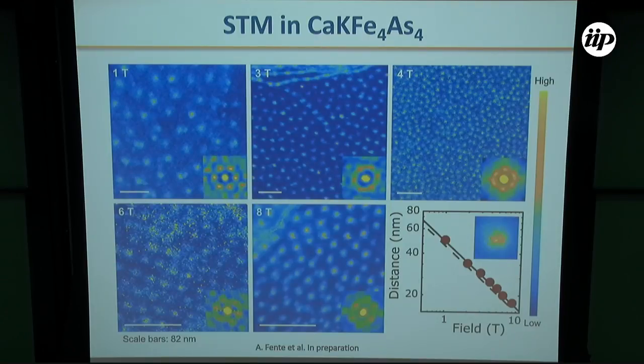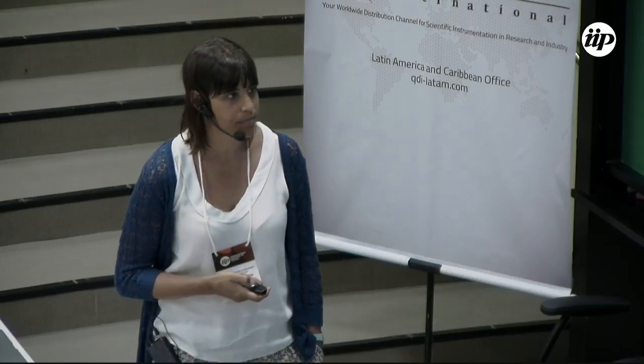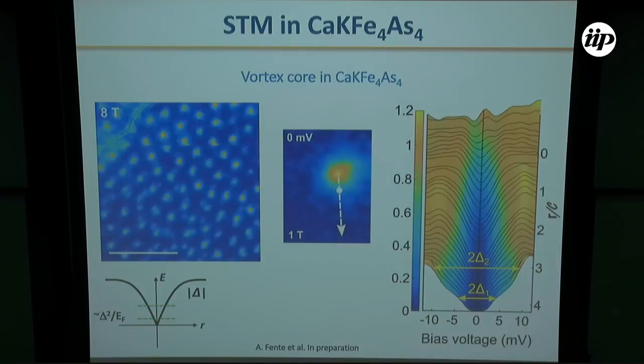The vortex lattice is quite disordered. The hexagonal order disappears after a few lattice spacings, and the intervortex distance behaves with the magnetic field as expected for a hexagonal lattice. We have also analyzed in more detail the vortex core. The vortex core has a round shape, which indicates that there is no in-plane anisotropy in this material.